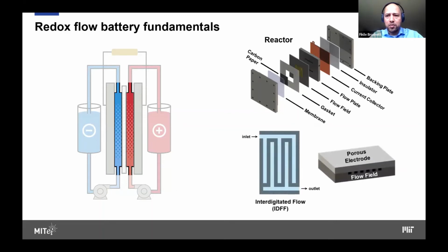The active species is brought to these porous electrodes through engineered flow fields. The example that I'm showing you there is an interdigitated flow field where the lighter blue areas are open channels and the darker areas are ribs. And if you look at the picture on the side there, those ribs then force the electrolyte through the porous electrode where the electrochemical reactions will occur.